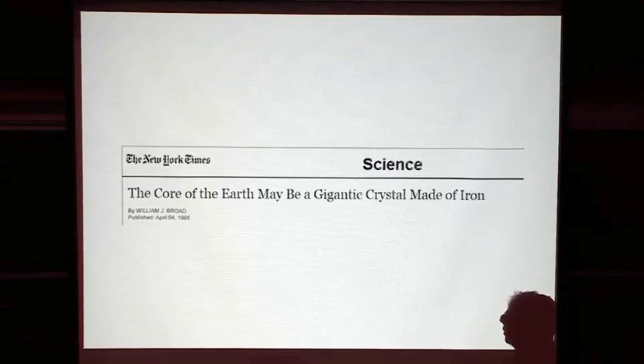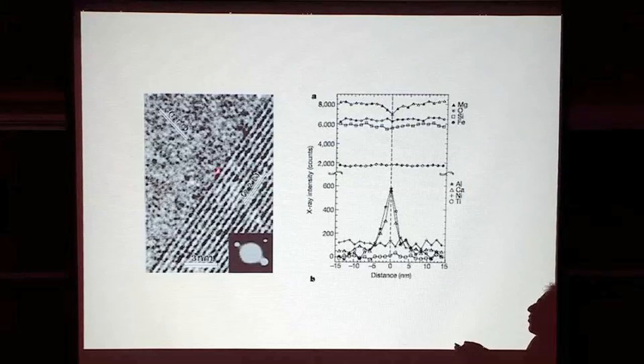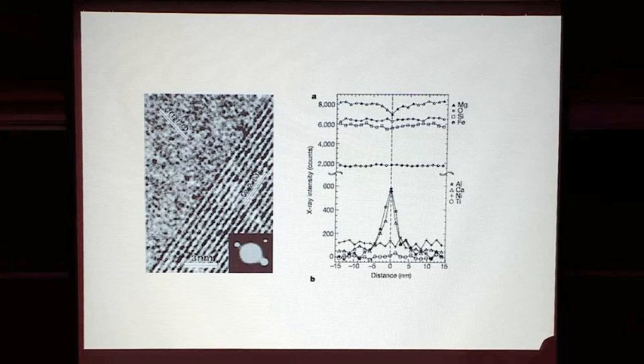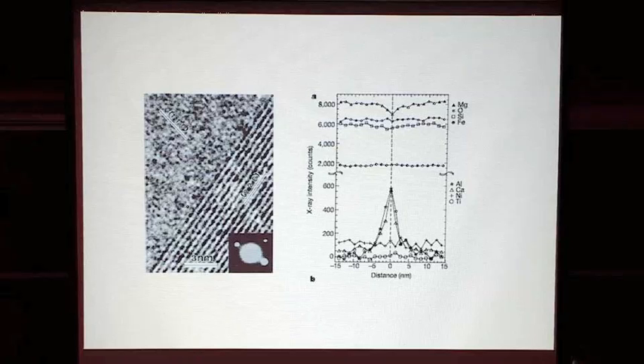If this is an olivine lattice, and this is an olivine lattice with a different orientation, we just need the monolayer over here to attach across the boundary with a different orientation. There's no need for it to overcome any potential barrier and diffuse across a lattice, like it would be for volume diffusion in a crystal. Just the local variation. Minimization of surface energy. Yeah, it's driven by surface area.